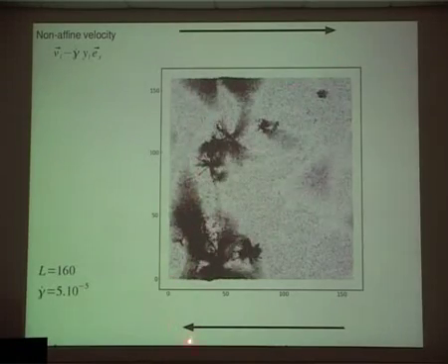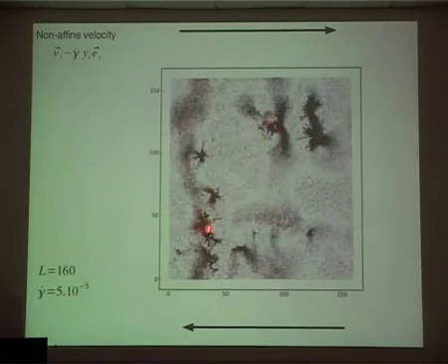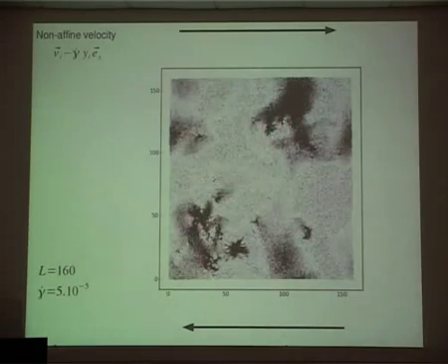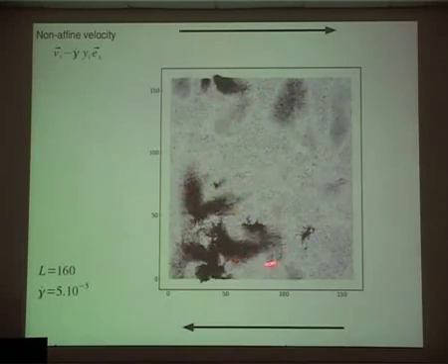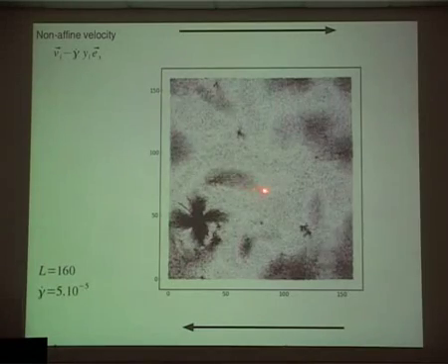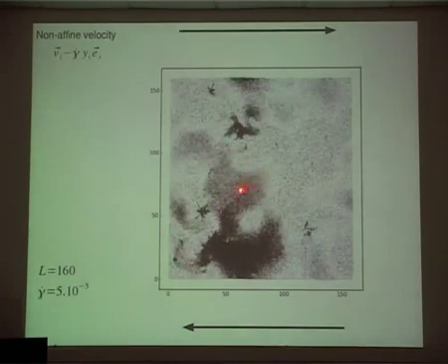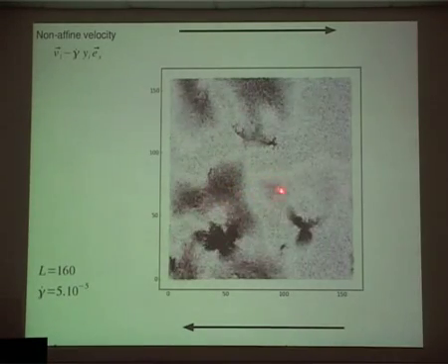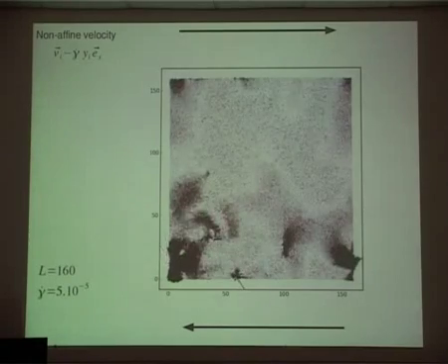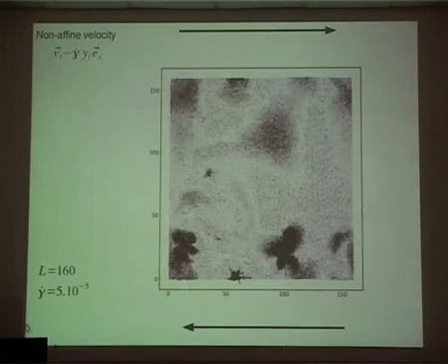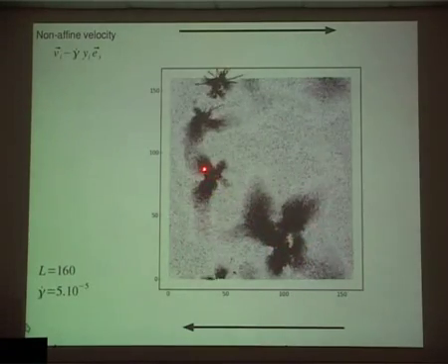So these arrows tell you how the system is sheared. And what we see, first of all, is tons and tons of shear transformation events. Everything I plot are arrows. The reason why you have some kind of shades of gray is just because you have very tiny arrows. And the variety of shades just tells you when you have larger or smaller arrows. When you have very big arrows, it's because in the center of this rearranging region, there are a few particles which move like crazy. And so they produce very big arrows. But essentially, these big quadrupolar-like patterns just correspond to local shear transformations.